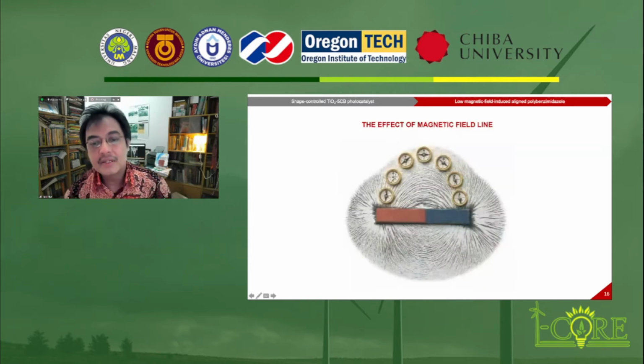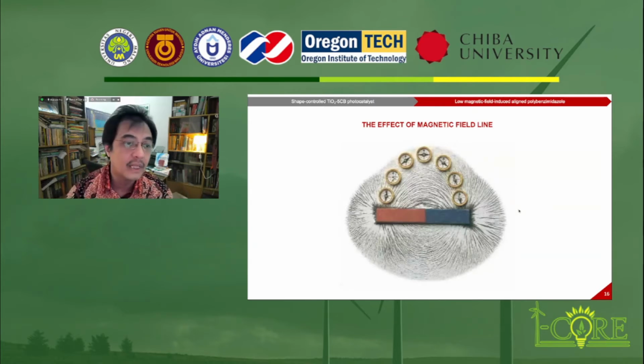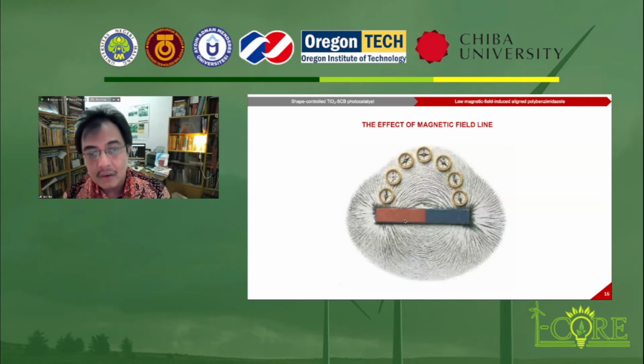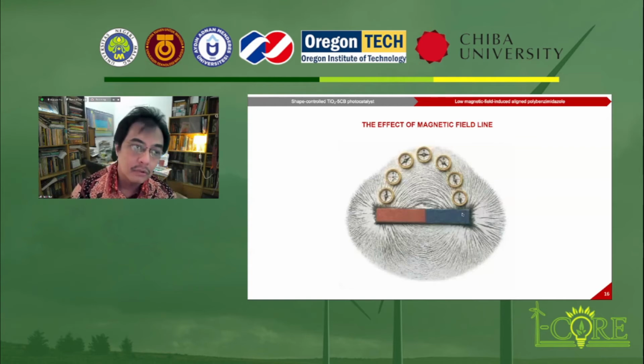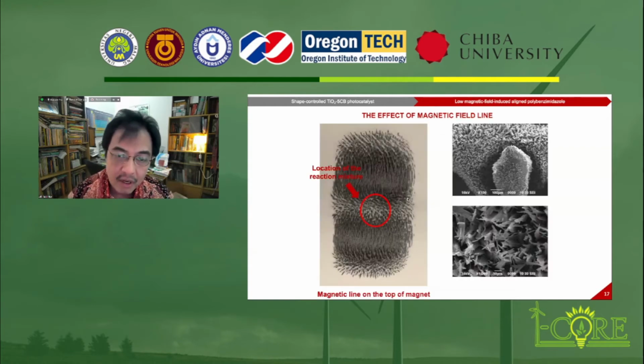The position of the sample on the homemade magnet apparatus also has an effect, because the magnetic field forms lines. This is the magnetic line. If we put iron powder on the magnet, we can see the magnetic lines. And the location of the sample with respect to the direction of the magnet affects the formation of the material.